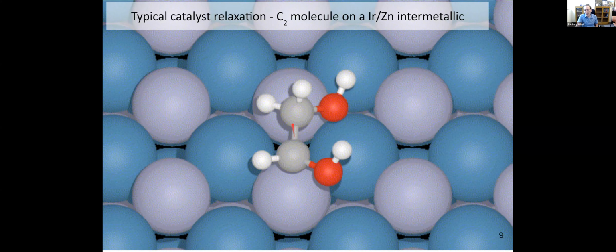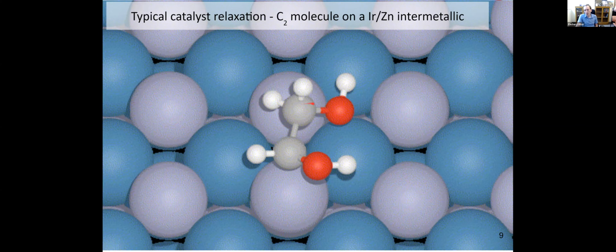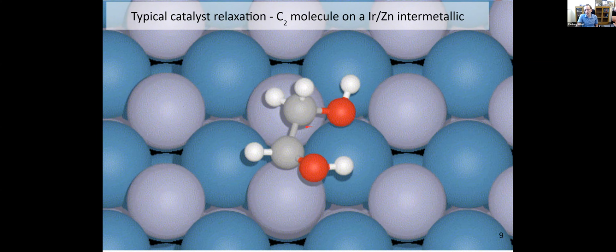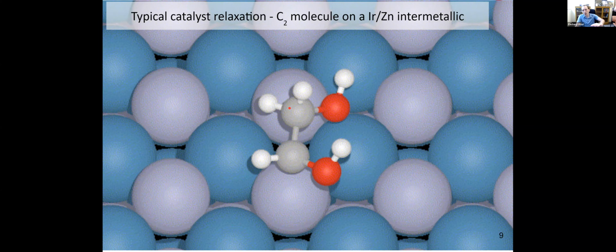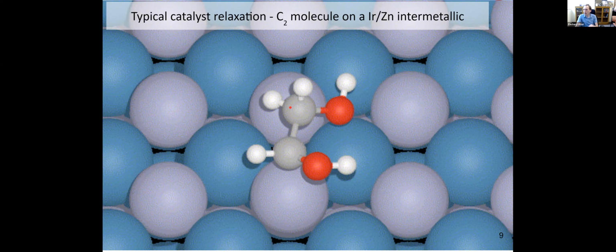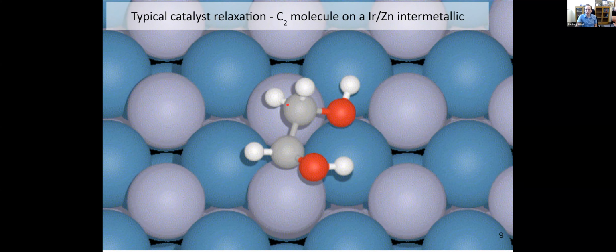And because of the additional degrees of freedom here and the fact that there's more atoms, this calculation often takes 4 or 5 days on a fast computer. And just think about all the different ways I can take this adsorbate, rotate it around, try different sites on the surface, right? The number of degrees of freedom is really, really, really large here. So this is why it's quite complicated.